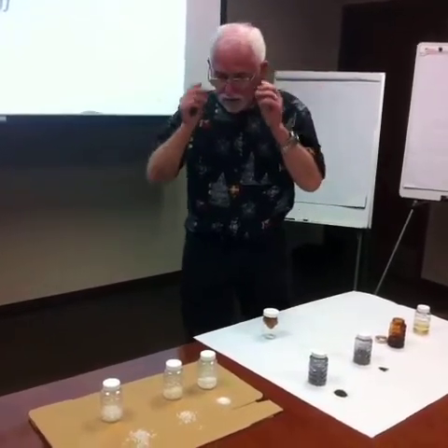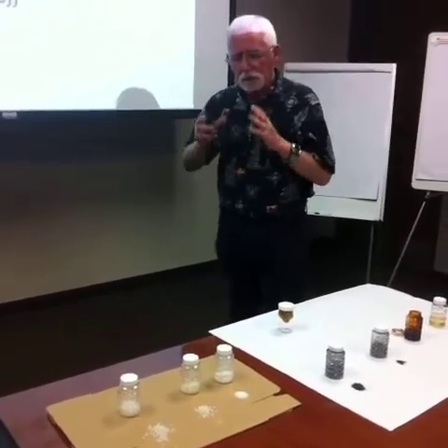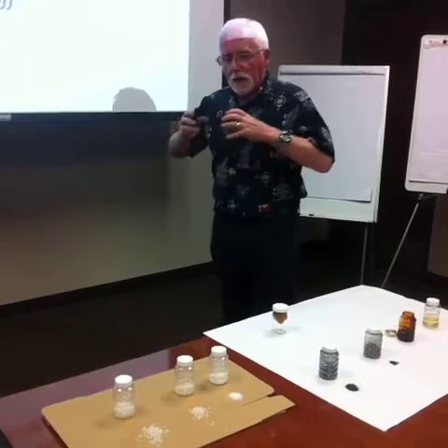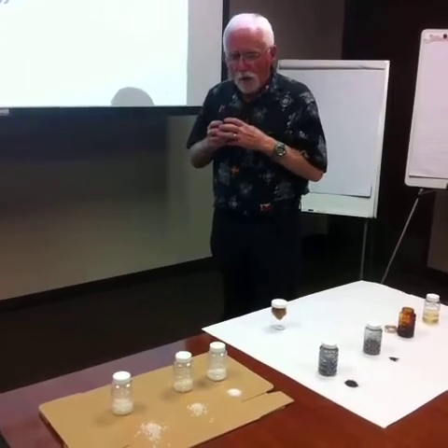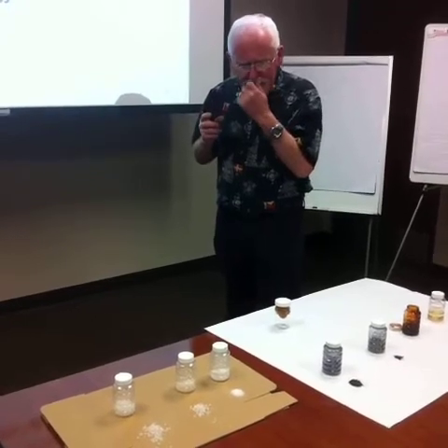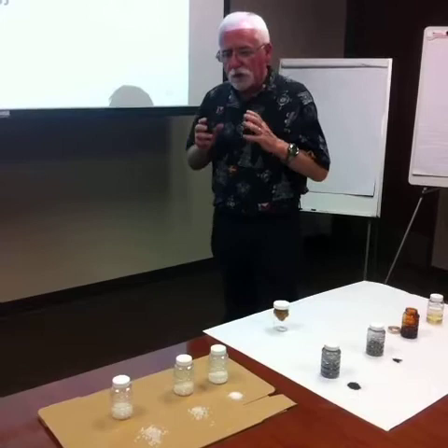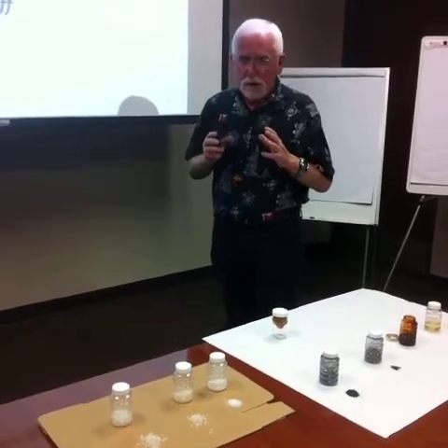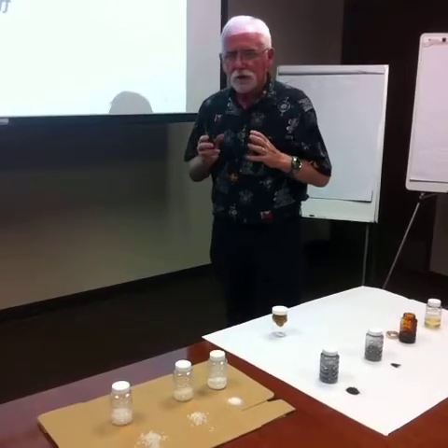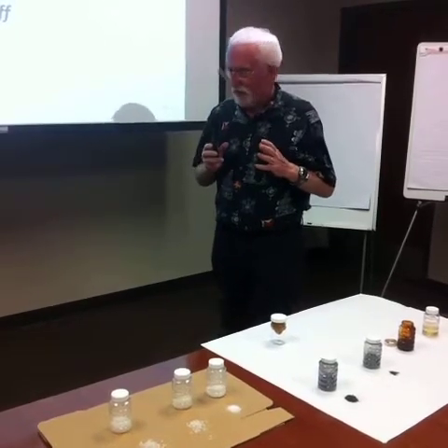And the first thing is, well, what is grease compared with oil? What's the difference? Grease is oil with a thickener, and the thickener holds it like a sponge holds water. That's the primary difference between an oil and a grease. Most of the thickeners used in grease are soaps, made very similar to the kind of soap that you take a bath with every day, but not sudsy.